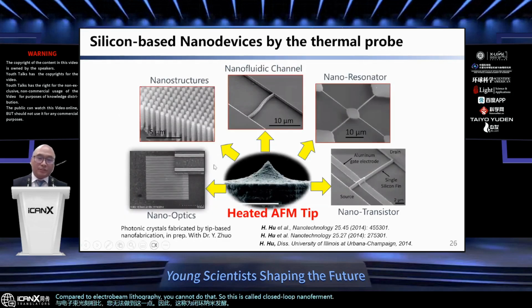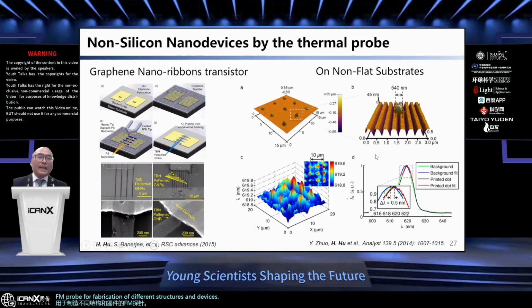So my PhD thesis just applied this thermal AFM probe for fabrication of different structures and devices. Okay, and in addition to silicon nanostructures, it's also pretty good for 2D material patterning. So we have done 2D graphene nanoribbons and made a transistor out of it. We can also deposit nano patterns of polymer on non-flat substrates. So with many lithography techniques, like electron beam lithography, you need to spin coat resist. But this one, we just do additive. So we can even add on non-flat or structured surfaces.